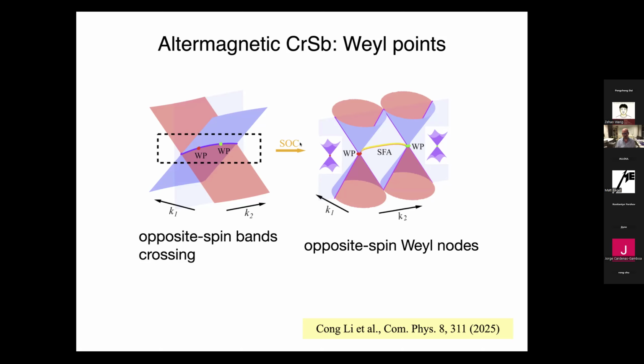Now, if you add, in addition, spin-orbit coupling, which always is there, these degeneracies will split, and either the spin-up and the spin-down band can gap out completely, or they can gap out in some parts of the momentum space and not in other parts of momentum space. And this gives you a Weyl point and Fermi arc.